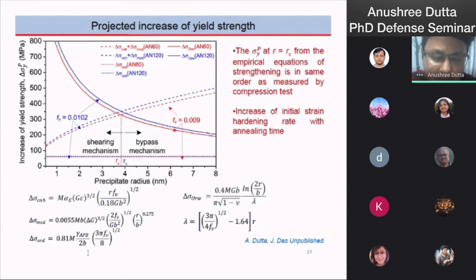In the precipitation hardened alloy, the lattice parameter of the precipitate phase is different from the matrix phase, so coherency strengthening occurs, and the shear modulus of the precipitate is different from the matrix phase, giving modulus strengthening. And because the precipitate is ordered, order strengthening is observed. The contribution from each strengthening mechanism is estimated for the precipitate shearing mechanism, and for the precipitate bypass mechanism, this is the Orowan mechanism.